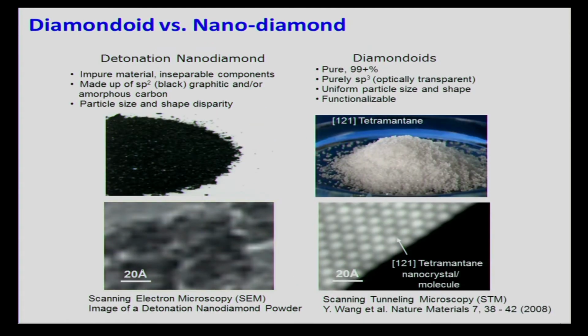So again, to compare the two species: what we know as the nanodiamond, that is the diamond made by setting off TNT in a jar, and what we call diamondoid, these chemically pure, shape-specific and size-specific diamond molecules or diamond structures that were extracted from oil. You can see that just from the appearance, they're quite different. One is a grayish or black soot containing a lot of different sizes, shapes, chemical compositions, etc. The other one, you can have available as a chemically pure and also size and shape pure chemical.